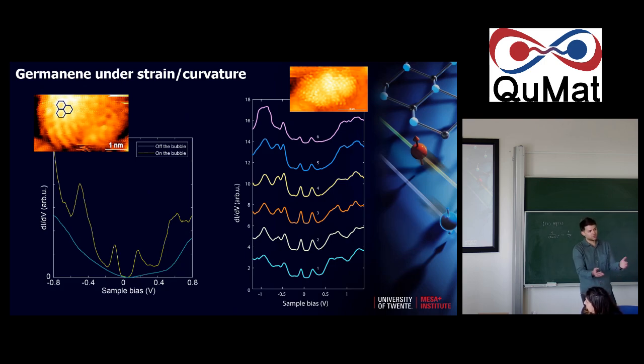So we think that this is doping. You have some doping, and then it shifts extra states from the Fermi level. And you see the same thing in the peaks. So if you dope the thing and make a bubble, you see that the peaks are also shifting. But it's not.